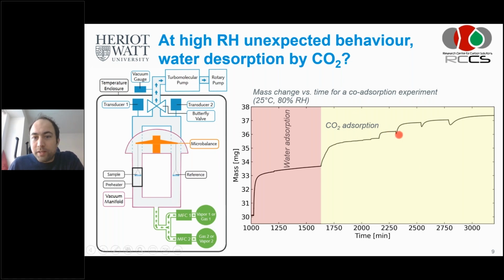This is fantastic. Here you see these dents in the graph. And so at some moments when we added more CO2, so we stepped to a new partial pressure set point of CO2, we see that some gas or vapor was desorbed. And we don't know whether that is water or it was CO2 that was already absorbed. And of course, first we assumed that it would have been water, but then we tried to close the mass balance for CO2 and it didn't work. So there's probably some mixed desorption going on. And that's a difficulty, and that's a challenge that we have now. We're also talking to Surface Measurement Systems about how we can further develop the DVS to be able to close the mass balance. But that's future work.